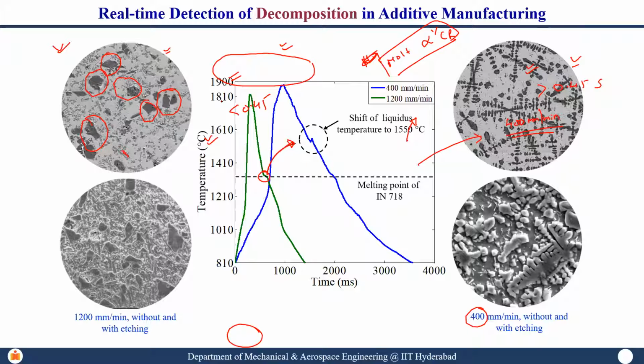Okay, so there is a difference between melting and dissociation. It doesn't melt here, it gets dissociated. If you keep this titanium carbide particle at elevated temperature for a longer time, and then this Inconel 718, if you look at its chemical composition, it has niobium, molybdenum, as well as titanium, which are once again strong carbide formers.